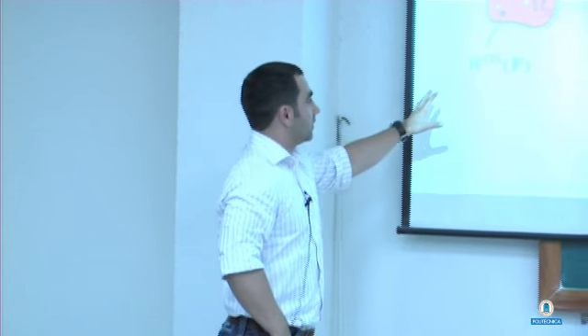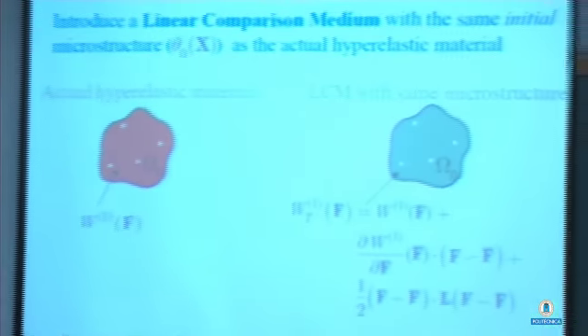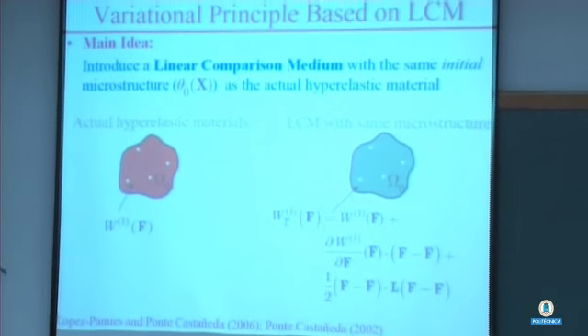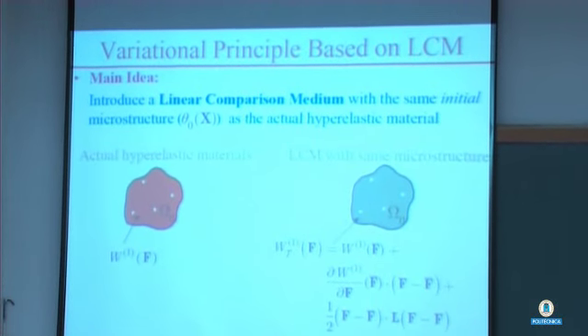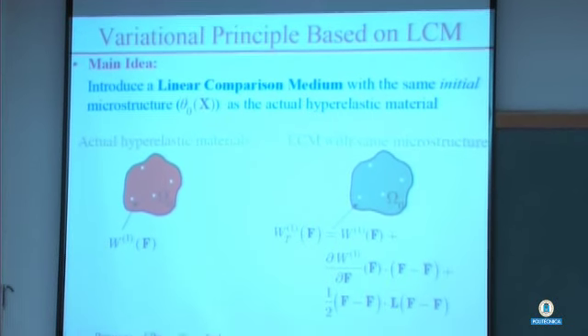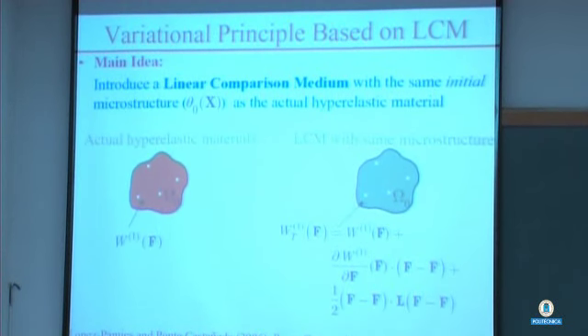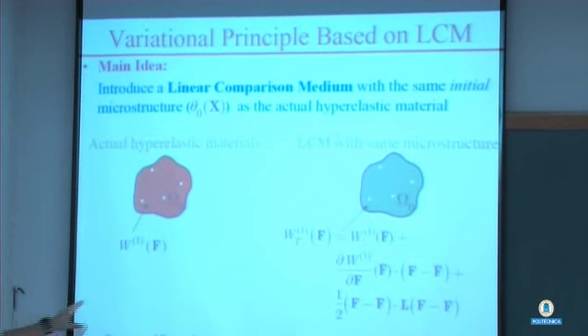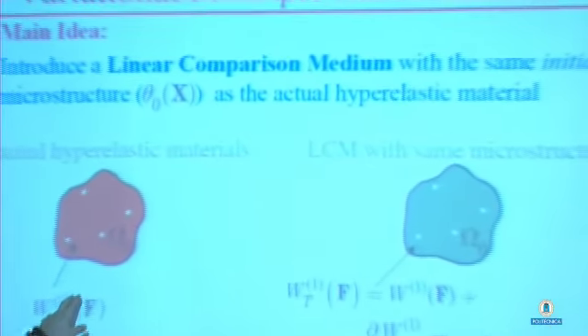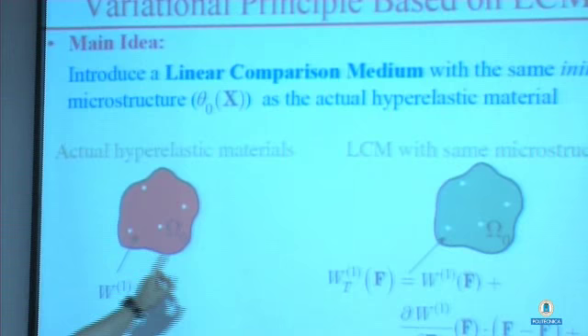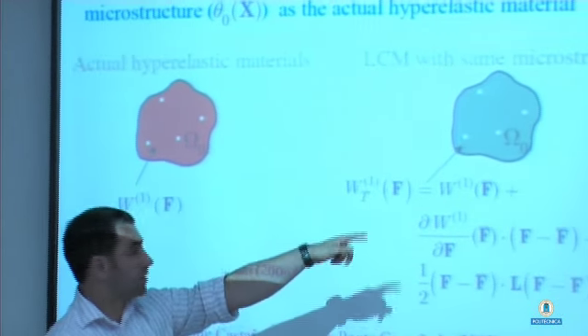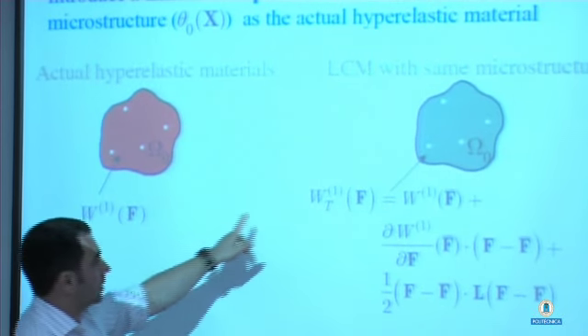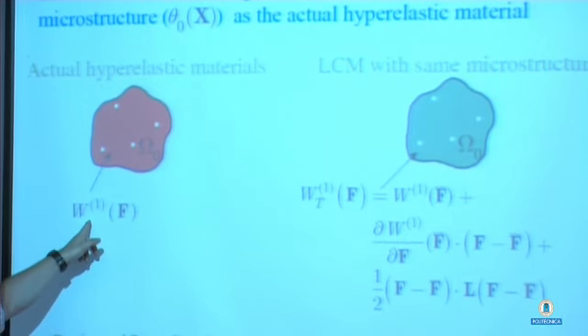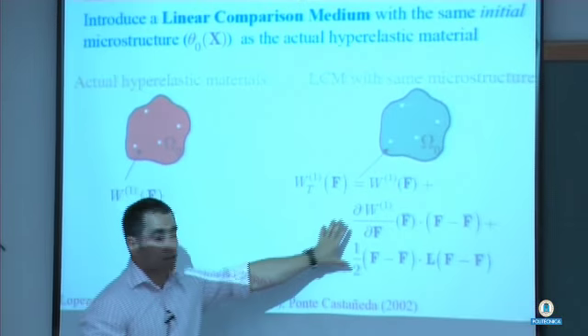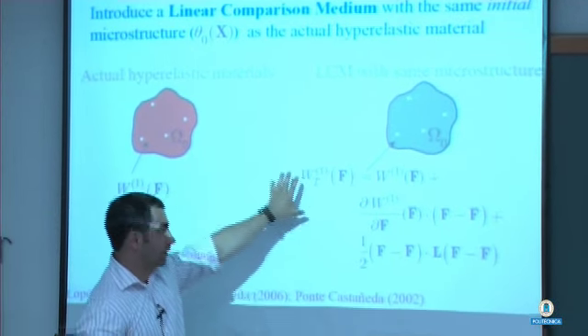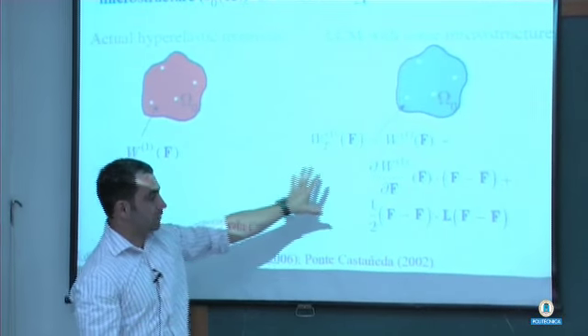So let me not jump here. Let me start with the idea. I'm not going to get into details, just give you the idea. What is this linear comparison medium method? So the main ingredient here is to introduce a medium that has the same microstructure as your material of interest, where the phases, in this case you only have one phase because you have pores, so you only have the matrix, is not characterized by this hyperelastic nonlinear function, right? But by a linear potential. Well, the potential is quadratic, so the stress-strain relation that you get from here is linear.